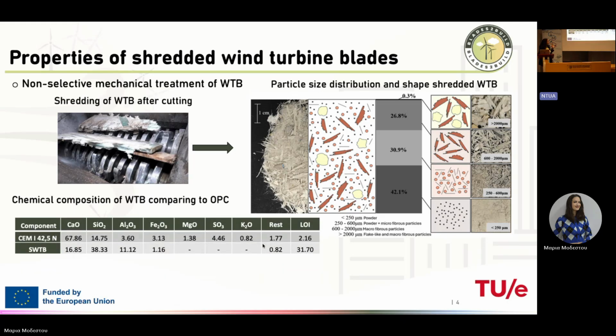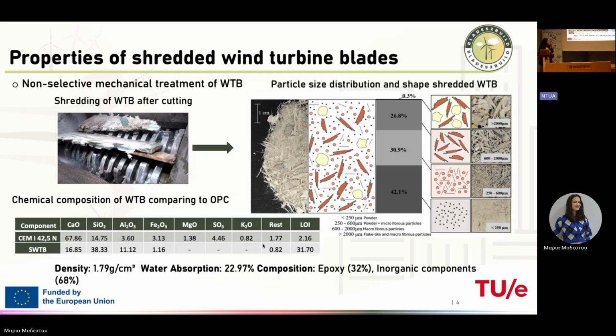If we go to chemical composition, we can compare the chemical composition of cement, the key material for concrete, and the chemical composition of wind turbine blade waste. Since we have loss on ignition of around 31 to 32%, we have this polymer component, and the rest is glass fiber. The density of this material itself is around 1.8 gram per cubic centimeter. Water absorption was around 23, and we had an epoxy-based composite with inorganic components, mostly glass fiber, 68%.